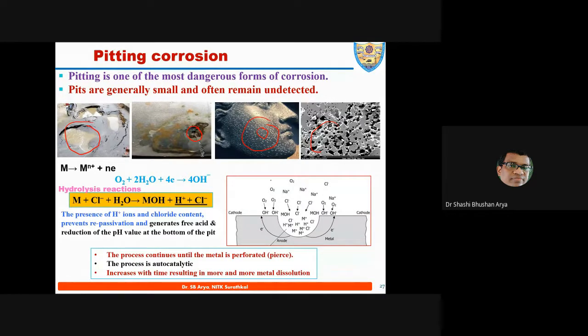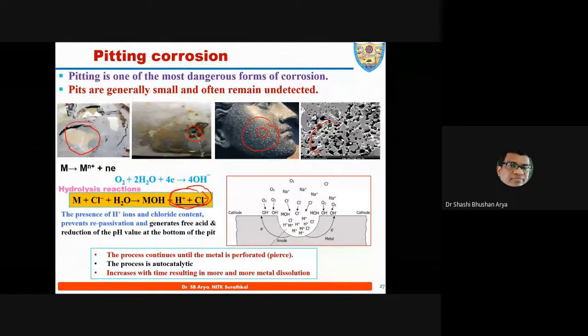So this is a typical failure because of film failure. Dissolution is there, and it will fail because of one extra reaction called the hydrolysis reaction. Inside the pits there is very low pH, that is hydrochloric acid. Because of that, the metal is not going to provide film stability, and that's why pit formation will take place. It is a micro-level size pit, but very deep, and that's why pitting corrosion is called a localized corrosion, but very dangerous. Uniform corrosion will give you a sign of brown color. Pitting corrosion will not give you any signature because the pits are very small, but the penetration is deep, and that's why corrosion is going to take place in a very catastrophic manner.